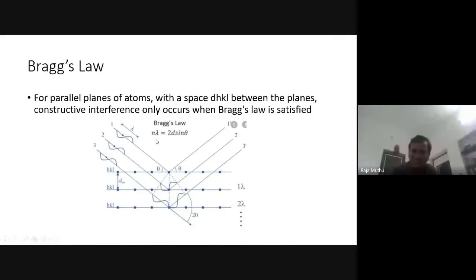See, for XRD, this lambda is fixed. The lambda is fixed because we know the wavelength of the particular X-ray. See the d spacing and sin theta. The d spacing and sin theta are inversely proportional. Since lambda is fixed, if theta is fixed, the d spacing is very important.